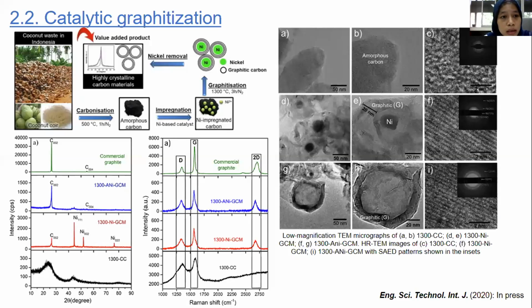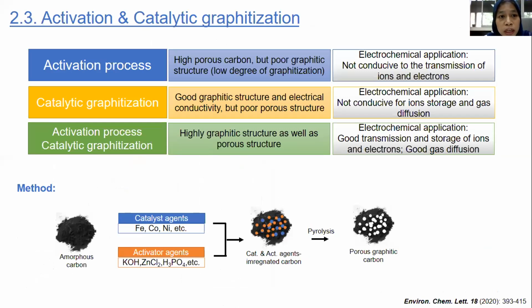Okay, next, the last mechanism is the combination of activation and catalytic graphitization. As I mentioned in the previous slide, the carbon structure from biomass obtained by chemical activation only has a good porous structure but low graphitic content, and it limits its application in the electrochemical field because the structure is not conducive to the transmission of ion and electron, while catalytic graphitization only, conducted on biomass-based carbon, produces a good graphitic structure but low porosity and surface area.